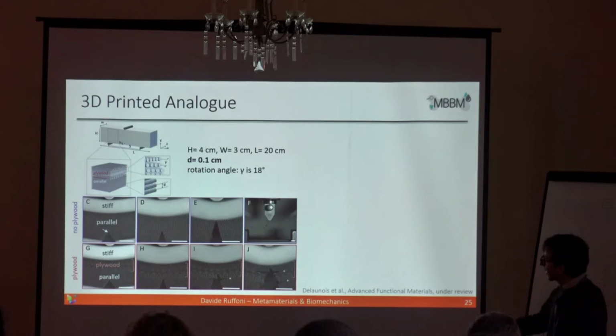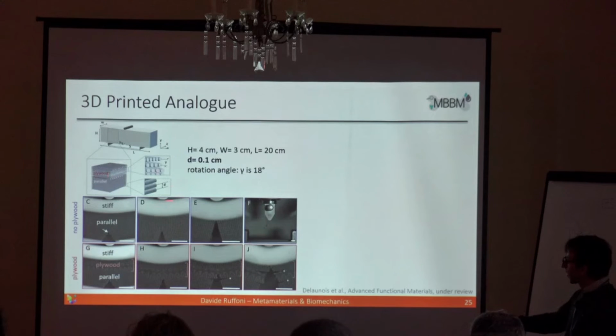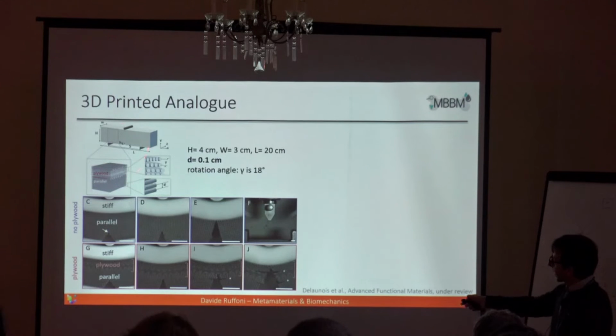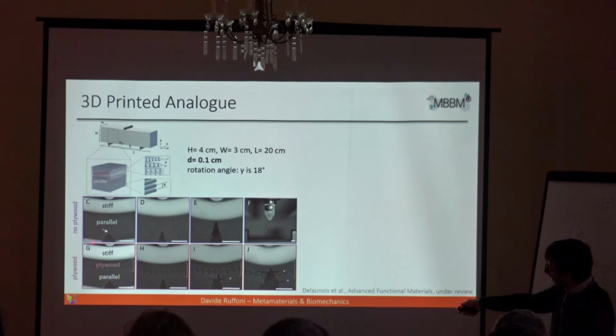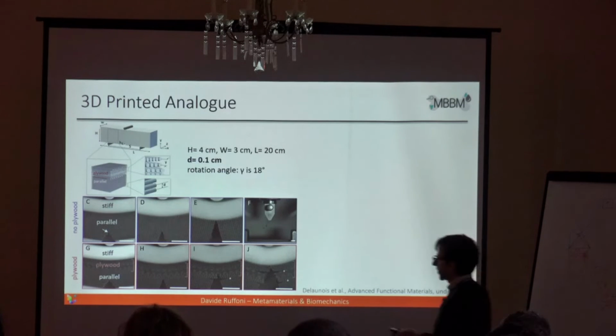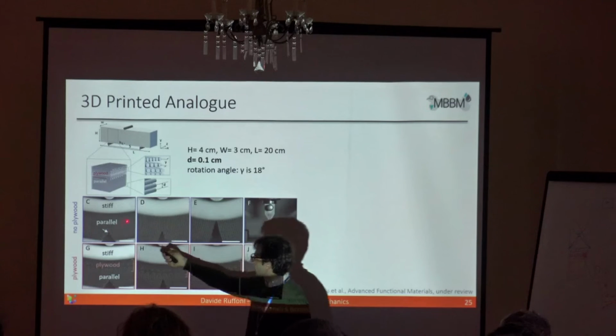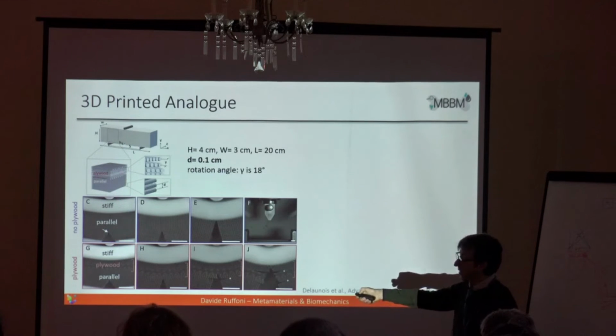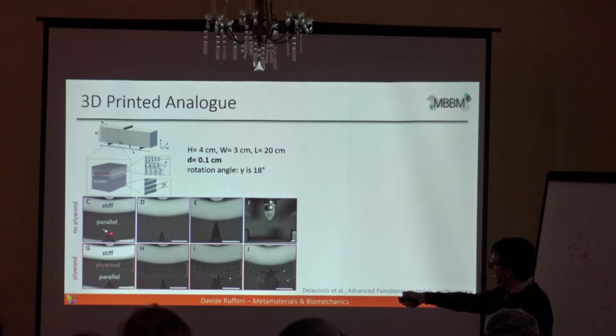And what we also did at the end, we tried to see if this system can also work in a kind of synthetic system. So we designed a specimen composed of an outer stiff layer, mimicking the outer mineralized shell, with 2 different designs. In this region here, we designed parallel stiff fibers, so they're coming out of the screen, and they are embedded in a soft matrix. And then we did some very simple 3-point bending tests to see how damage that starts from an initial notch propagates.